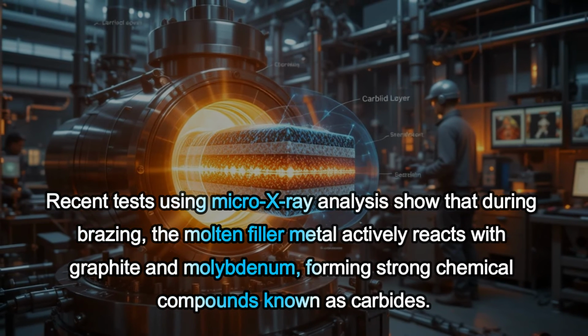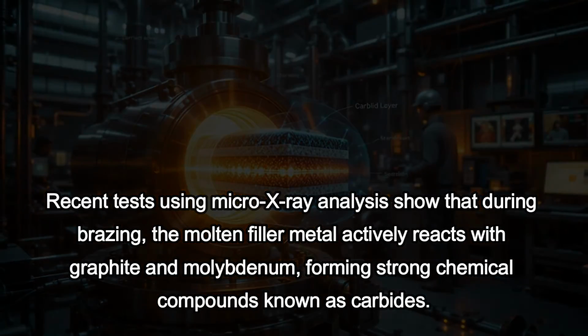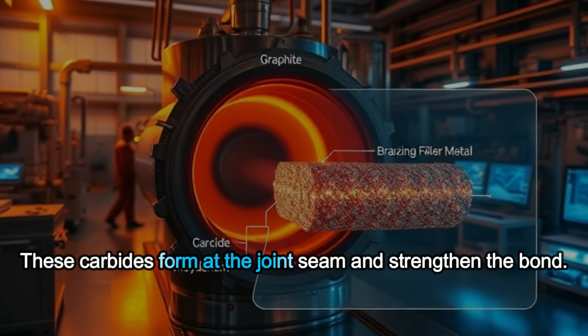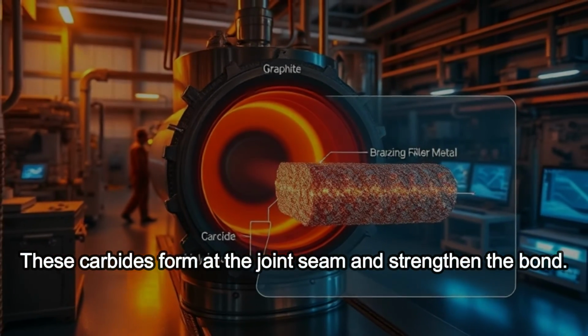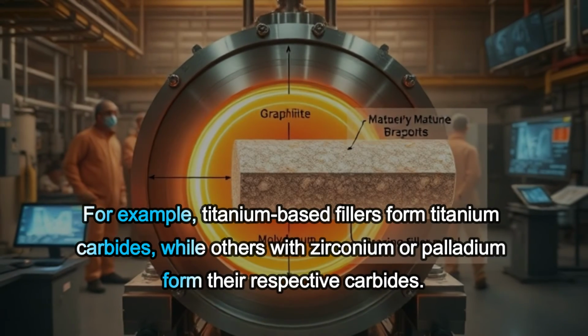Recent tests using micro-X-ray analysis show that during brazing, the molten filler metal actively reacts with graphite and molybdenum, forming strong chemical compounds known as carbides. These carbides form at the joint seam and strengthen the bond. The type of carbides depends on the filler metal used. For example, titanium-based fillers form titanium carbides, while others with zirconium or palladium form their respective carbides.